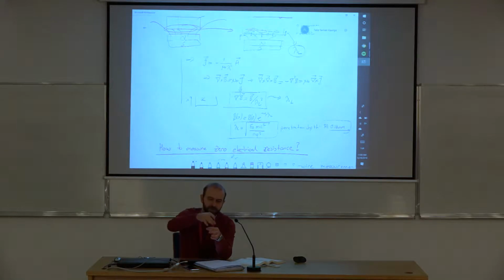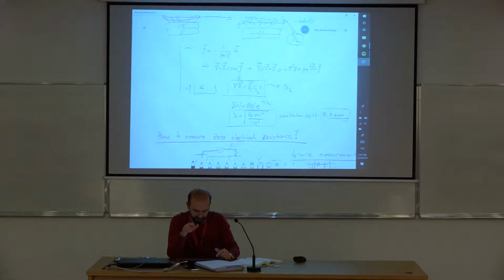In the copper pipe, when you drop a magnet, as it travels through, because of the magnetic field, it creates eddy currents, which oppose the magnetic field, so it creates a force, and that force can resist the gravity. But copper is a lossy material, so you cannot create these superconducting currents. But in this case, you can create superconducting currents, which can create equal force to carry the weight. So the idea is very similar, but the mechanisms are different. They have the same physical reason in very basics.